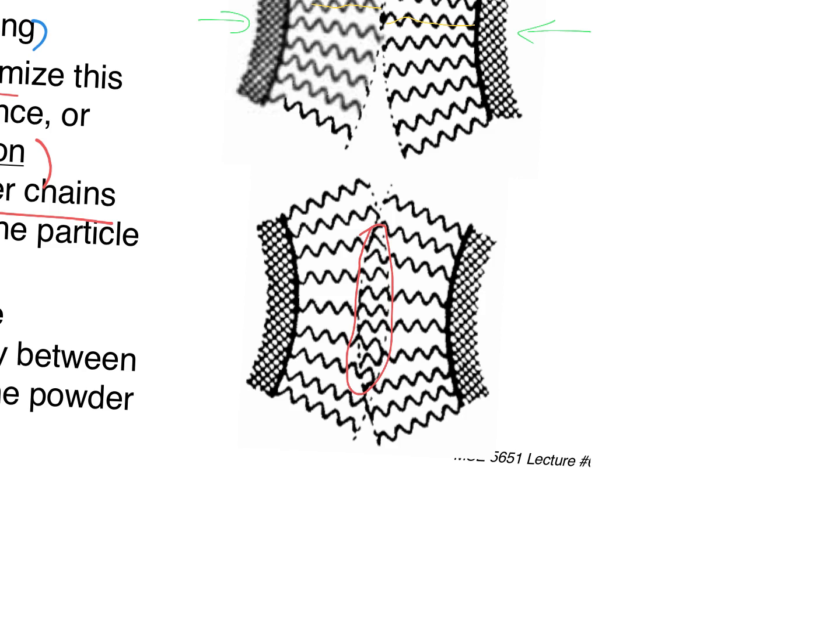And then the energy of the system goes up because polymers don't like that. They like to be as random as possible. And what you're doing here is you're packing them together and you're taking away some of that randomness, all right? So what happens is we have this entropic barrier that is generated when you try to drive these two polymer coated particles close together. All right, so what that does then is it pushes them back when that overlap occurs.